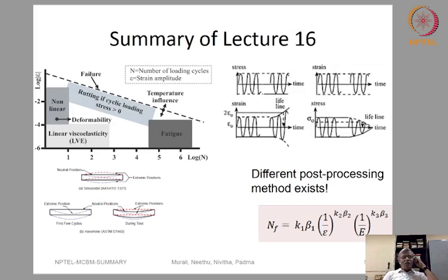So one needs to very clearly understand, if you look at the top left picture, the strain versus the number of cycles, fatigue is always at this end, which means the load application that you give will result in strains that are substantially less and the number of cycles will be more. And there is a linear viscoelastic regime that you will see at the starting point, because there is going to be energy dissipation due to the viscoelastic behavior, and if you go slightly up you get into the non-linear deformation, and the temperature influence is also indicated.